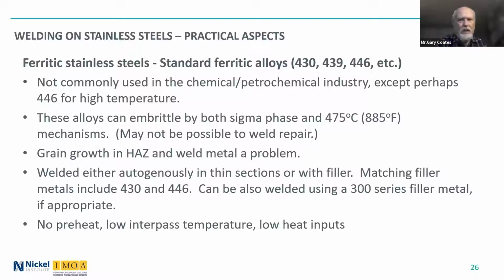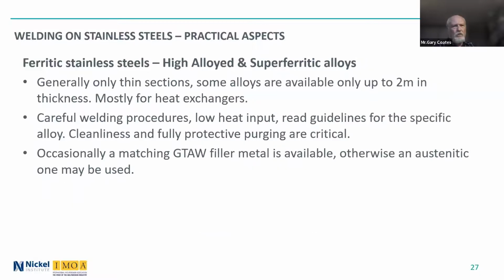You want to weld them with a matching or a ferritic filler metal. And most of these alloys, you don't need a preheat. You do want a low interpass temperature and low heat inputs on them. And that's all to prevent grain growth.